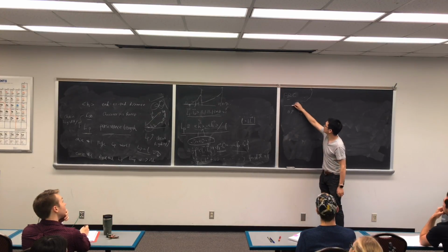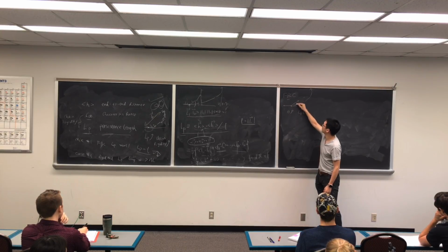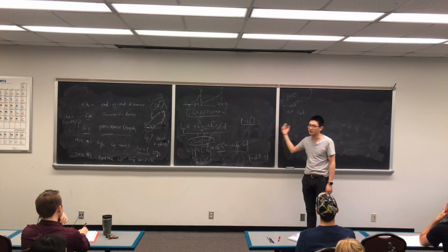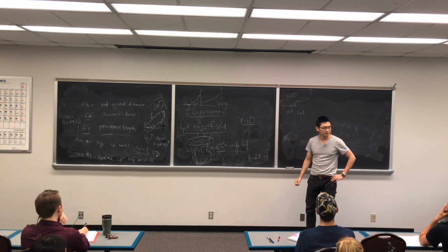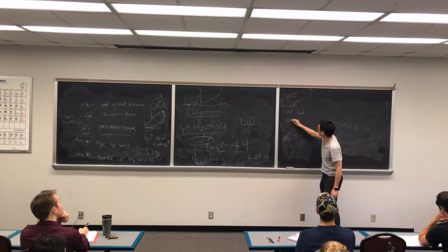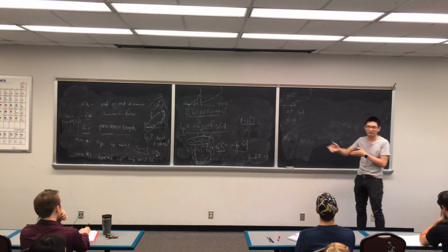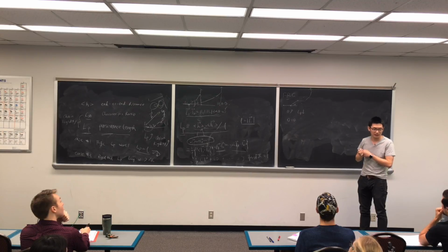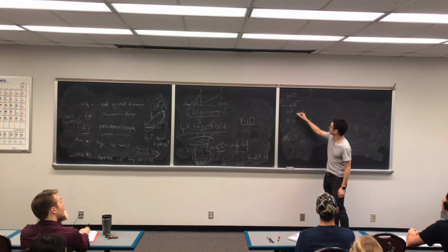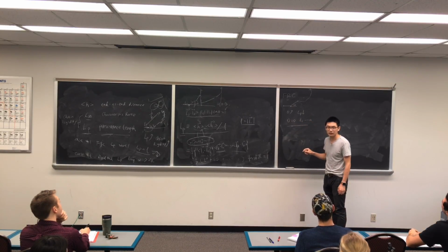Because the bigger the theta angle between the neighbor bonds, so this is a carbon, this is another carbon, the more likely it is to quickly pass the 90 degree bend angle. On the other extreme, if you fix theta as 0, you're going to have a super rigid chain that will have a super long persistence length, right? Your LP will go close to infinity, just because every bond is kind of straight in this case.